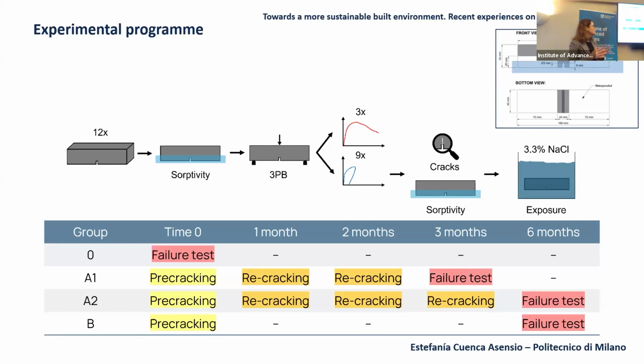We also perform another test that we call the sorptivity absorption test. This is particularly interesting because it allows us to quantify how the crack is healed, but in depth, also in the inner part, not only at the surface. For sure, it is also interesting from a mechanical point of view. Very quickly, the sorptivity test is an absorption test. We subject these prismatic specimens, 4 by 4 by 16 centimeters, to water absorption across the notch on this side, because the rest is waterproofed with silicone. So it's a unidirectional flow.